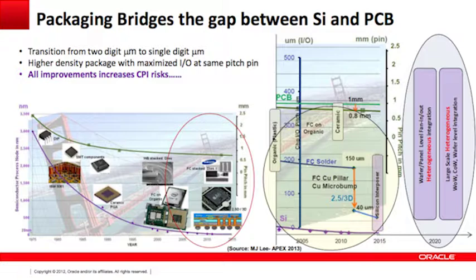Those technologies feed through all the way to BGA, and now some package-on-package. If we break down an iPhone or Galaxy cell phone, you may see all these kinds of packaging technologies there. From 2015 and moving forward, even within the package and substrate, between silicon and package, we need finer pitches. Typical flip chip solder has a limitation at 150 micron pitch, but we need more and more. So it goes to 40 micron, and eventually 30 micron is coming soon. Silicon interposer can make it happen these days.